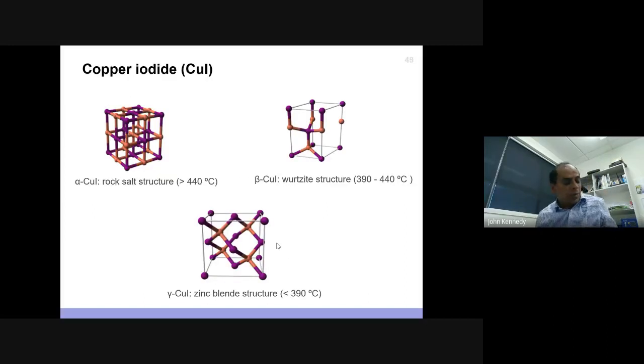So what we did is we looked at copper iodide, which is really interesting because copper iodide is a P-type thermoelectric material. The crystal structure is a zinc blende structure similar to the other one, and it is predicted to have a figure of merit of more than 0.2 at room temperature. 0.2 is still high relative to other organic materials, but it's not like 1 like bismuth telluride. But we thought, let's see whether we can do something here with the nanostructured form, because you have a large surface area, which might help when you deposit these films, and might help to reduce the phonon scattering and thermal conductivity issues.